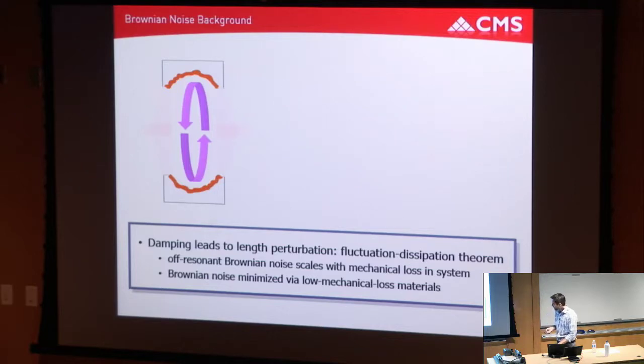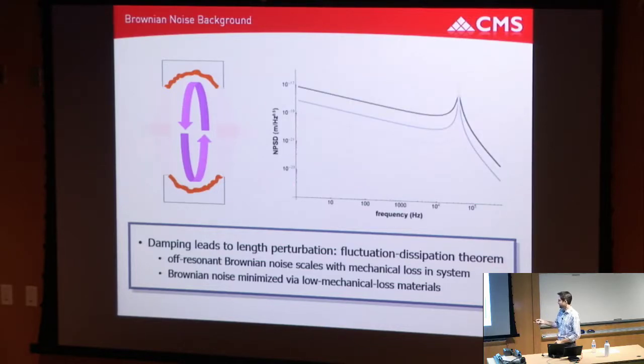If you plot the noise power spectral density of that cavity as a function of frequency, here I'm pulling out just one isolated mechanical resonance of that body, and I'm plotting it with three quality factors shown, with increasing quality factor going here. Keep in mind, this is one random mechanical mode for that body. I'm probing it way off resonance at some low frequency, below the mechanical resonance. And as you can see, as I increase the mechanical quality factor, I start to pack the noise in and around the resonance, and I pull down the off-resonant tails.